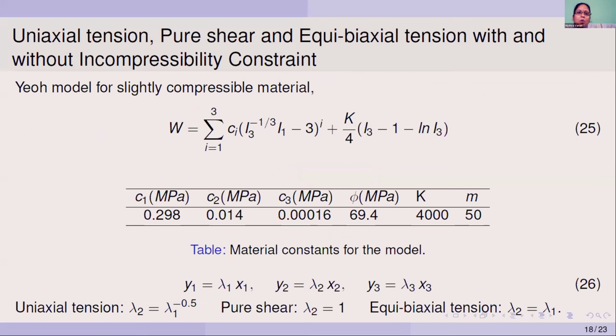So in both the problems that we considered now, we have imposed an incompressibility constraint. So let's now relax this incompressibility constraint and study the onset of damage in a sheet of slightly compressible material, when this material is subjected to different cases of uniaxial tension, shear strain, and equibiaxial tension.